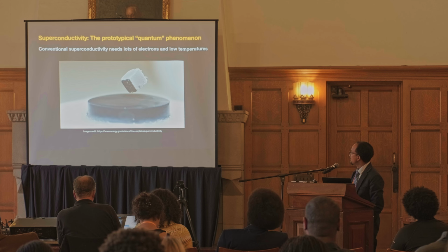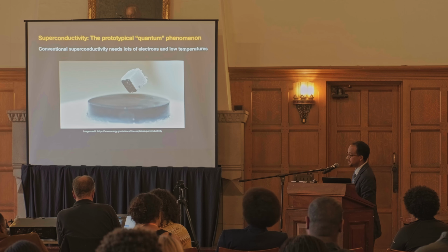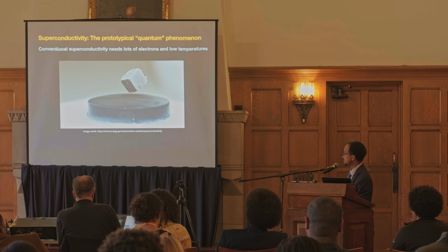Usually, superconductivity requires large densities of electrons, and you need to be at very, very low temperatures. That is conventional superconductivity. And there's a very good reason for that related to the mechanism, which we understand. Conventional superconductivity is mediated by lattice vibrations of a material. It's called BCS theory. That is well understood, but that's not going to get us to superconductivity at room temperature anytime soon, or in any realistic system under ambient conditions.